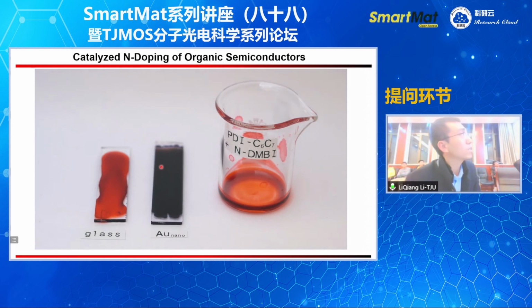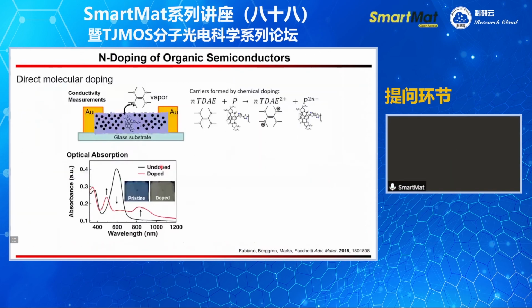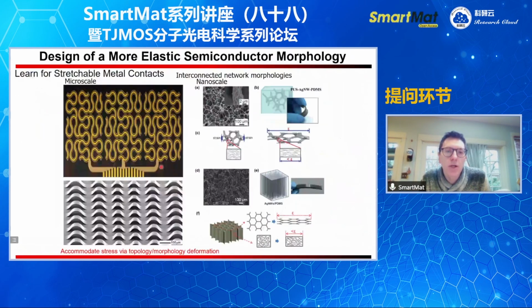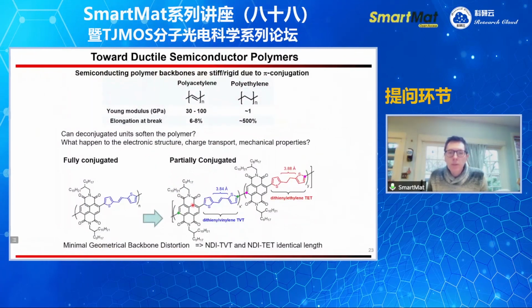My second question is about the deconjugation method. How to control the deconjugation degree? Yeah, the reaction is done by a polycondensation reaction. So we use a dibromide of this material, and we use a distannylated of these two building blocks. This is the work we published a few years ago. The kinetics, the rate by which these two monomers react, are identical. So basically, you mix these two in a certain ratio, and you end up with a polymer which incorporates the units in a certain ratio. So it's a random copolymer incorporating a given quantity of the red and the blue components.